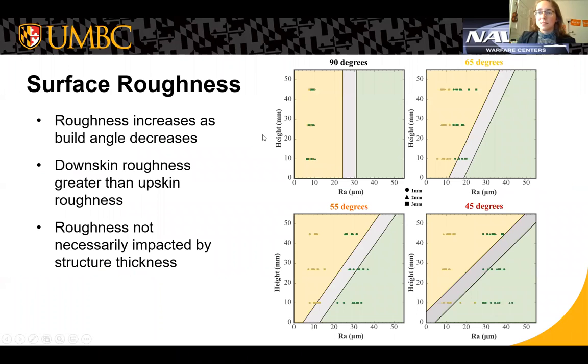We can actually see this in the data. We used 2 types of methods to measure the surface roughness. One was using a stylus and one was using a Keyence confocal microscope. The confocal microscope was really helpful for allowing us to visualize what we were looking at, but this data here is from our stylus measurements. And what we saw here is, again, the roughness increases as the build angle decreases. Likewise, the downskin roughness was a lot greater than the upskin roughness in almost all cases, except for 90 degrees, which technically doesn't really have an upskin and downskin surface.